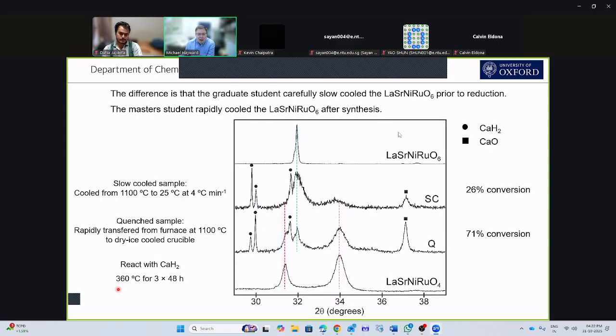And what I'm showing you now are the X-ray diffraction patterns that come from that process. So the pattern on the top is the starting material. The pattern on the bottom is the final product, the reduced material. And then in the middle, we've got patterns from a slow cooled sample and a quench sample. And what we can see is that the quench sample has reacted much further than the slow cooled sample. The slow cooled has only converted about 25%, about a quarter of the material, to the reduced phase. Whereas the quench sample has got 70%.